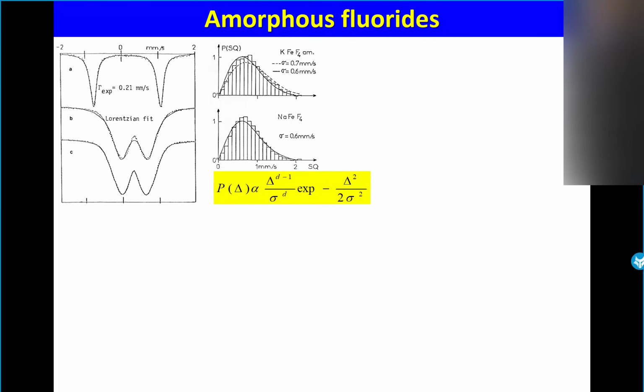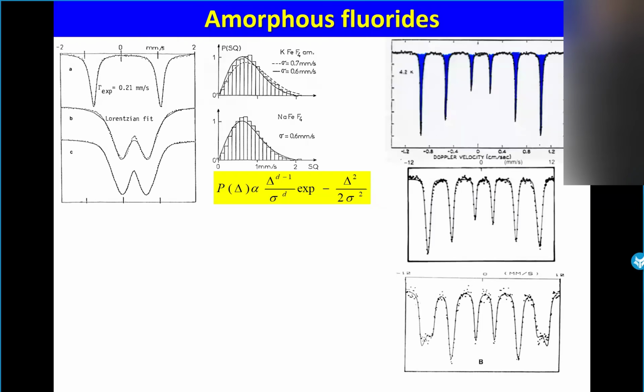What you can see is the doublet is perfectly symmetric. That means you have a single value of isomer shift. A single value of isomer shift means you have only octahedral units. So the amorphous phase is composed only of octahedral iron units. Okay, so it is possible to model this kind of distribution. And it was funny because at the same period, the people who were working on metallic glasses gave the same conclusions.